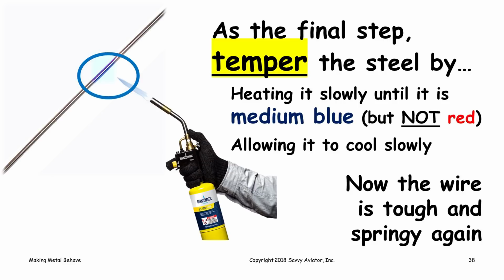And this step is called tempering. So the process, again, is to anneal first, which softens the material, then bend it to the shape we want it. Then we harden it by heating it and quenching it, and that makes it really hard, but it's too hard for the application. And then we temper it, which makes it just right, by heating it up not nearly as hot and allowing it to cool slowly. It's kind of like partially annealing it, if you will.